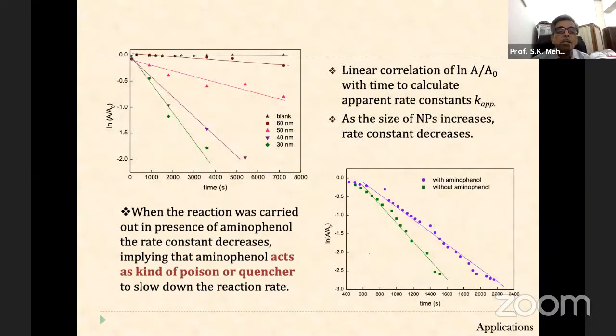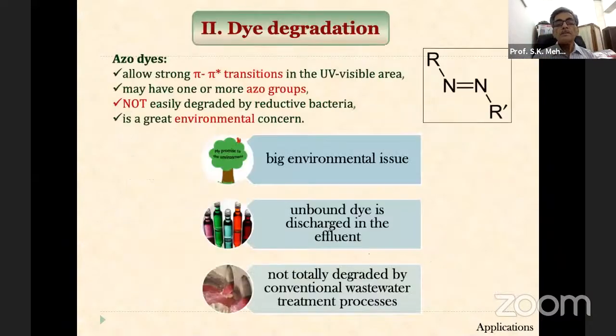And what we did, we modified all the parameters, wanting to see how much time it will take, when the reaction is carried out in the presence of the nanoparticles. But we found that aminophenol can also act as a poison or a quencher, and it slows down the reaction. So we wanted to see how fast the reaction is going, and till how much time it will stop or hinder. So we found that.